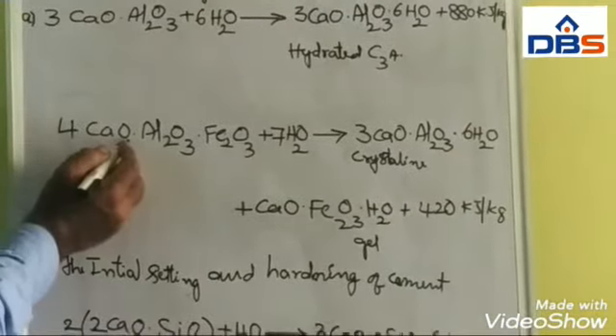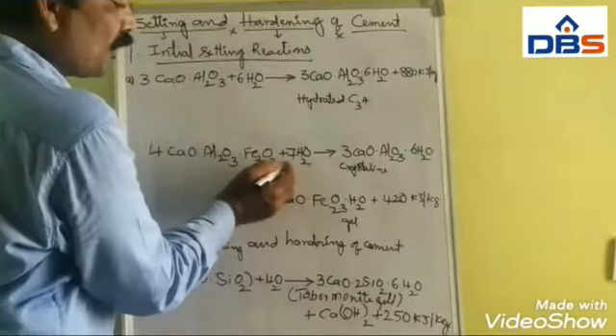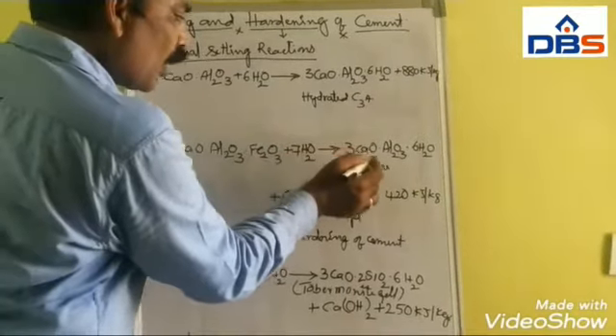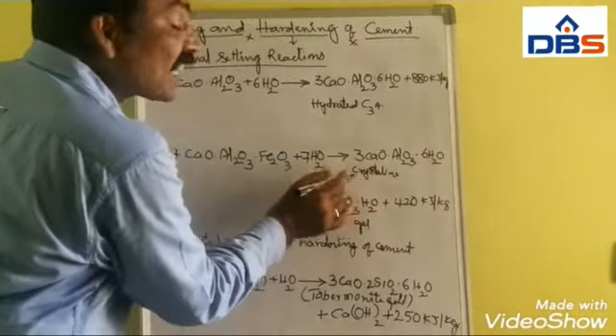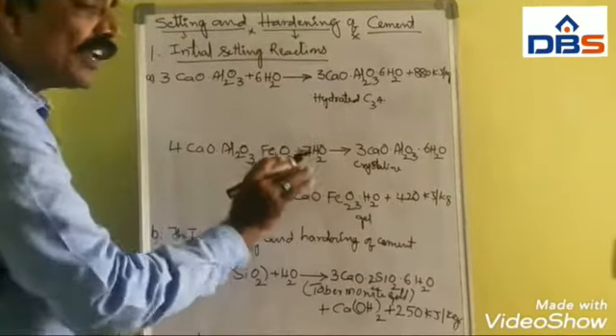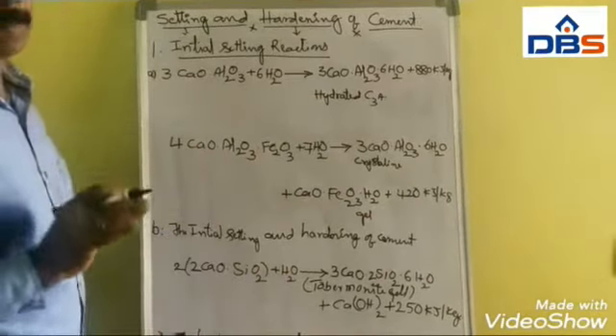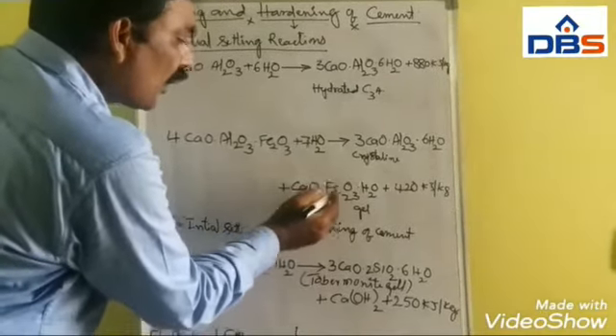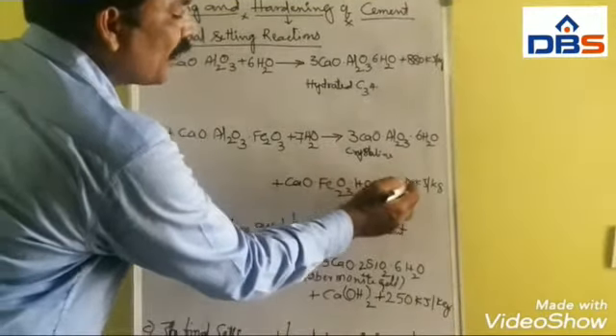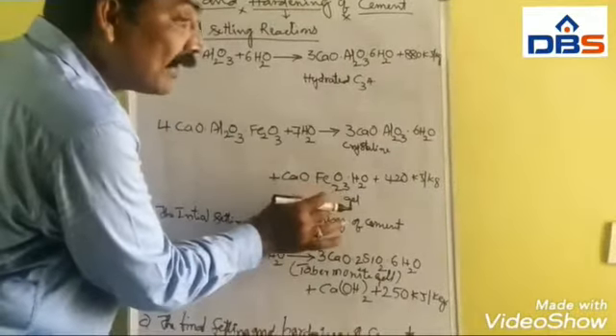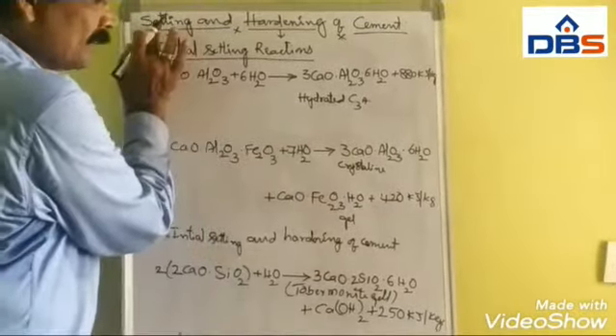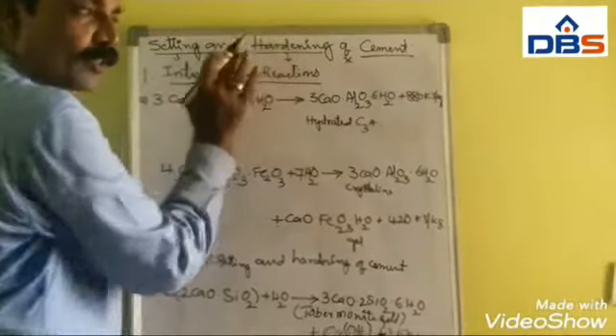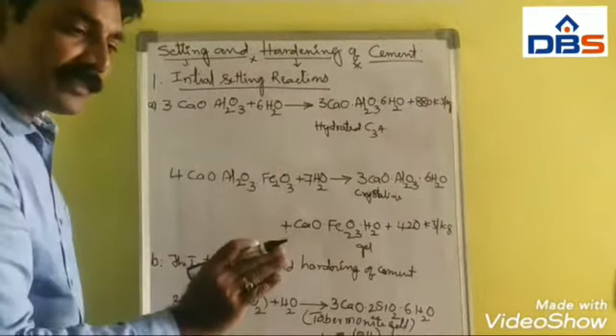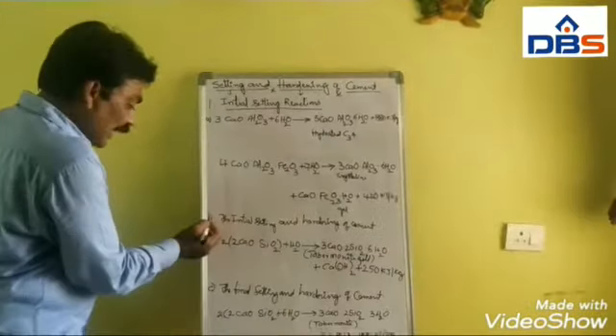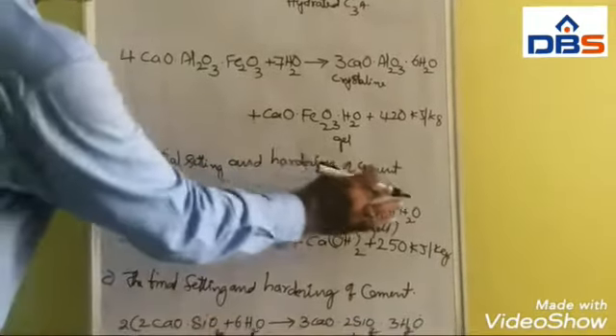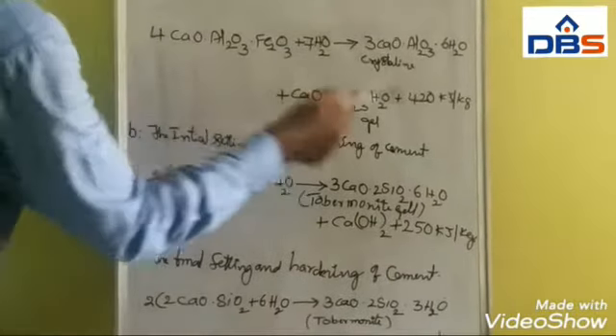The second one is 4CaO.Al2O3.Fe2O3 plus 7H2O gives 3CaO.Al2O3.6H2O, that is crystalline, which slowly sets to harden, plus CaO.Fe2O3.H2O plus 420 kilojoules per kg. This is the gel; gel formation is the setting. Crystallization is the hardening. Slowly, in the plastic mass, it will harden. The second one is the initial setting and hardening of cement.